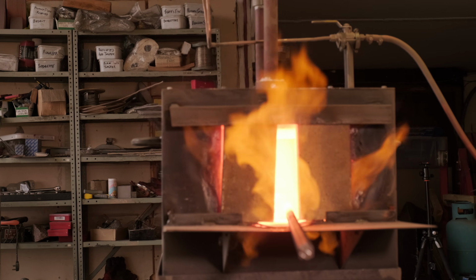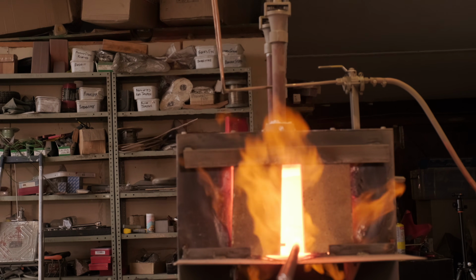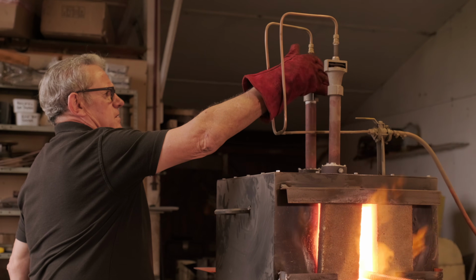So I use a gas forge. I make my own gas forges. They're very simple boxes made out of refractory brick, little burners in the top which blow air in, Venturi burners, and you've got an air control on the top of them which you can shut down the amount of air. Now, it's very important to have that, because that is how you actually control the atmosphere inside your furnace. Now, you've basically got three atmospheres you can have inside the furnace: a reducing atmosphere, a neutral atmosphere, or an oxidizing atmosphere.